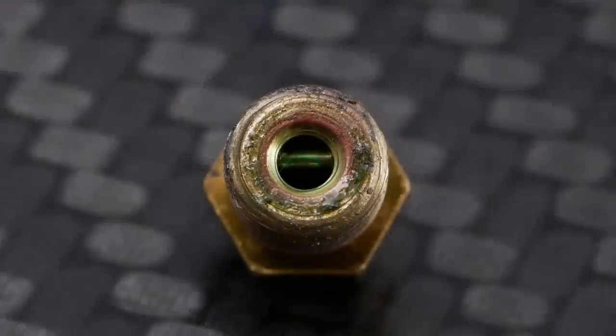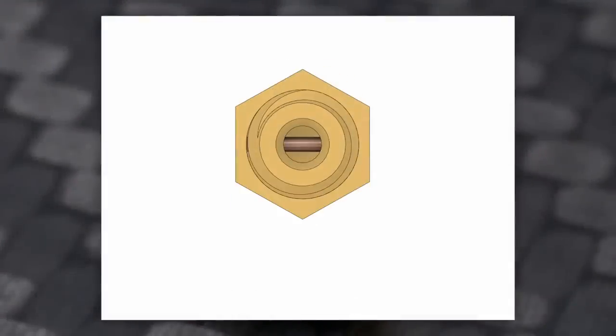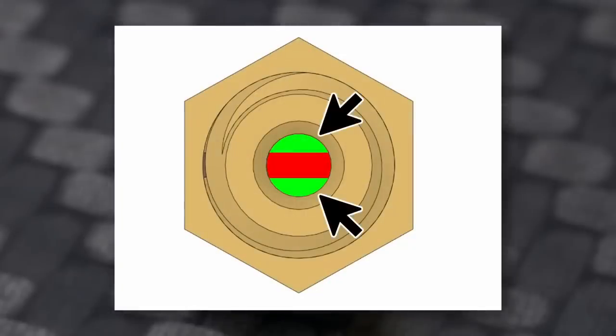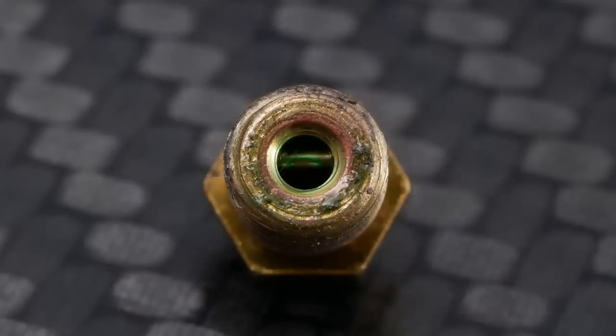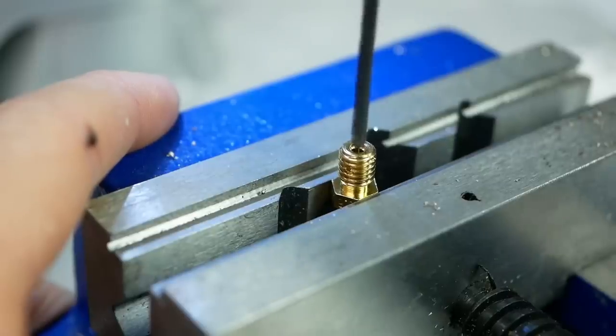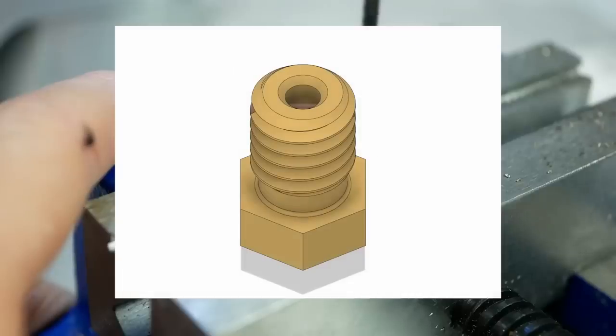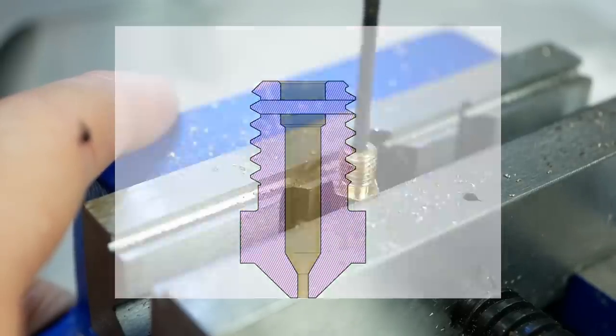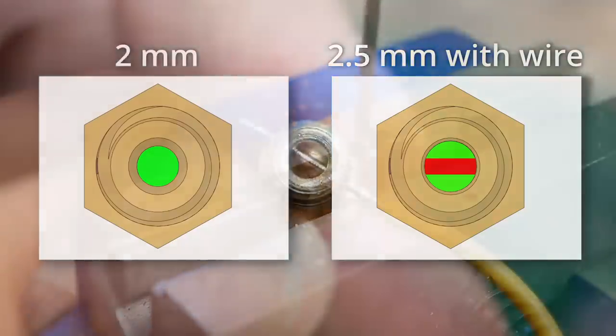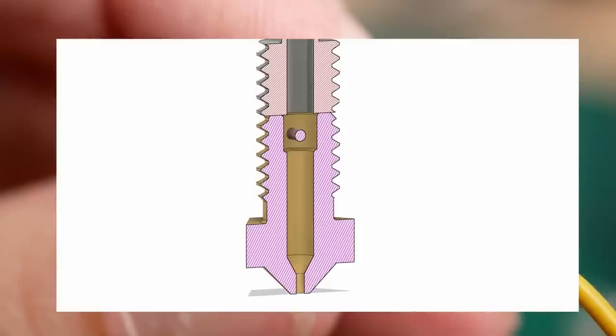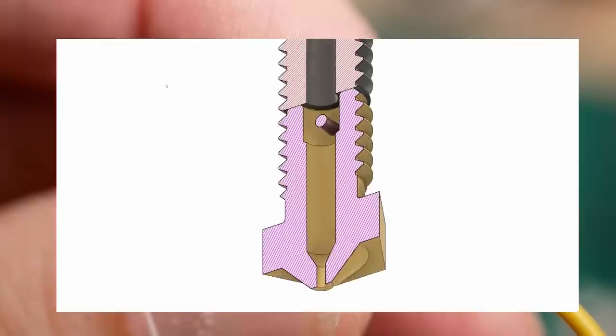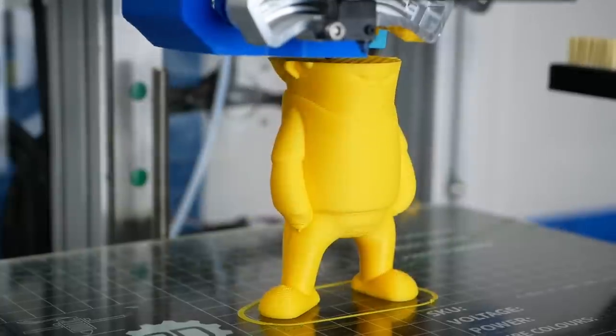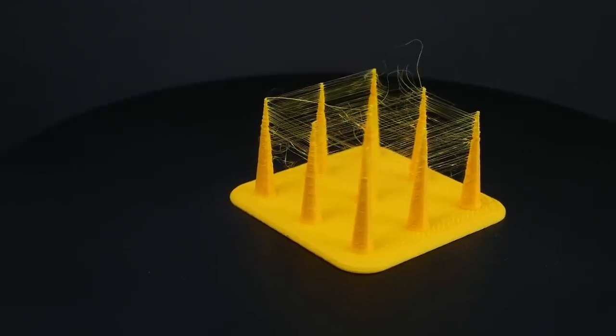But let's take a look at the geometry of our DIY high-flow nozzle. Adding the piece of wire significantly decreases the hole area within the nozzle. This means that even though the wire is helping with the melting rate, the added resistance again decreases the flow. I tried to get around this by increasing the bore size where the wire is from 2 to 2.5 millimeters so that the resulting surface area is similar to the unobstructed one. This adds an undercut at the transition to the heatbreak, but from my previous tests with the CHT nozzle and test prints with this one, it doesn't really impact retraction performance.